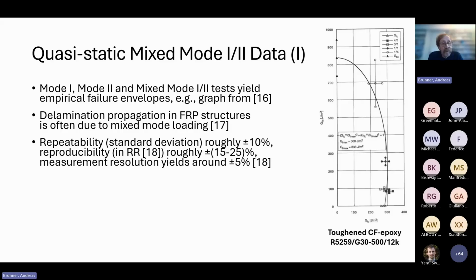Interestingly, if you try to estimate what the maximum scatter is that you can expect from the required measurement resolution in the standards, you get something like plus minus 5%. So there are external factors that produce a lot of scatter, and in this reference 18, I discussed some of that, if you're interested in more details.